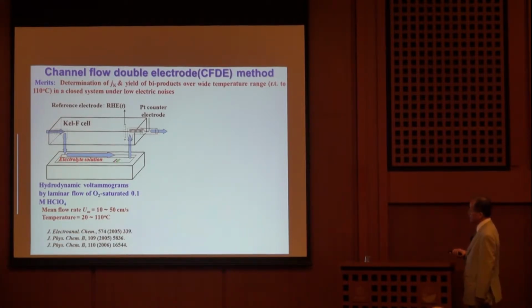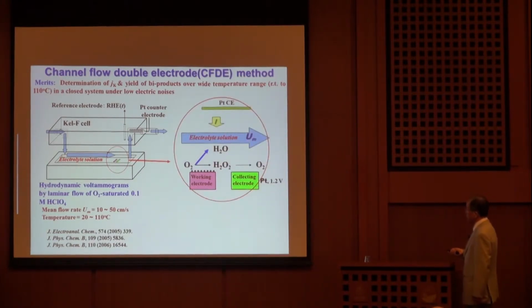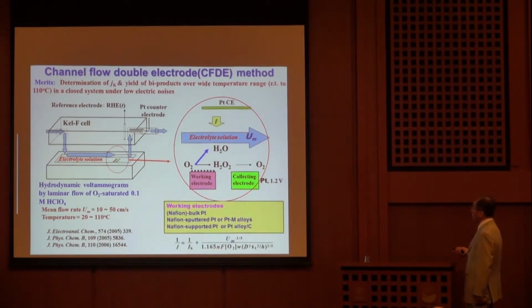And electrolyte, where dissolved oxygen or some other reactant is in the electrolyte, flows over the catalyst surface. The working electrode consists of bulky platinum or sputtered platinum or platinum precious metal alloy, a non-precious metal alloy, and also the Nafion coated supported platinum or platinum alloy on a carbon support, as shown here. And byproducts are also detected at the collecting electrode.